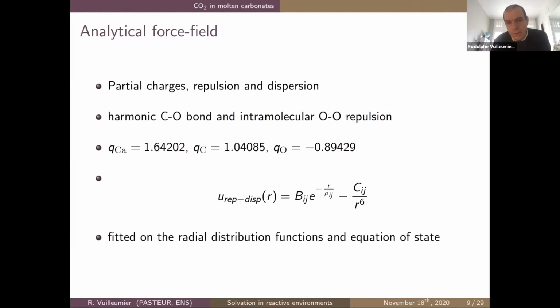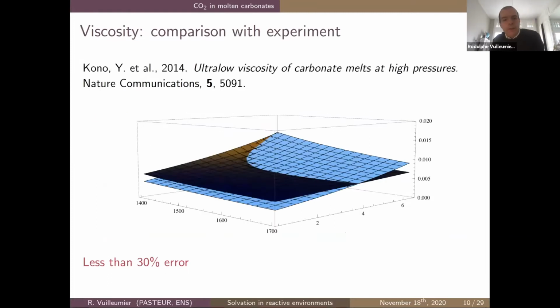But this is certainly the way to go, as we have addressed before in the workshop: to go from first principle MD to larger scales by a force field. And with this, we could compute indeed the viscosity as a function of temperature, so on this axis in Kelvin, and as a function of pressure in gigapascal.